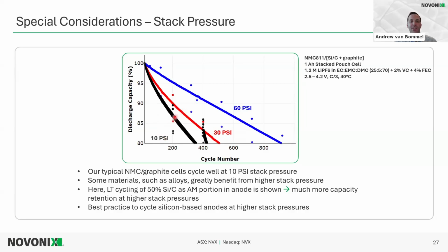So we have 10 psi in black. This is normalized discharge capacity versus cycle number. This is C/3 cycling. And then we have in red 30 psi, in blue 60 psi. So our standard is to have our stack pressure as higher, up to 60 psi, especially when we're looking at formulations of up to 50% silicon carbon, 50% graphite as the active material in the anode. It's important to have higher stack pressures, such as 60 psi. If we're lower, maybe 7%, 10% silicon carbon, we might get away with 30 psi cycling.